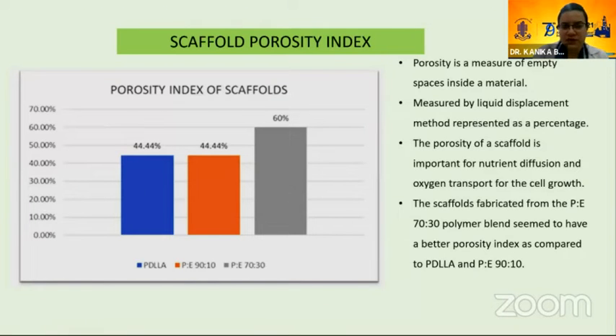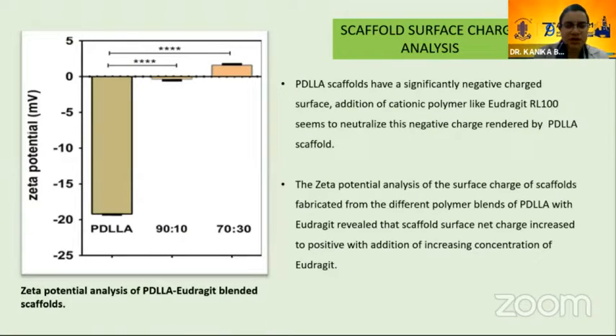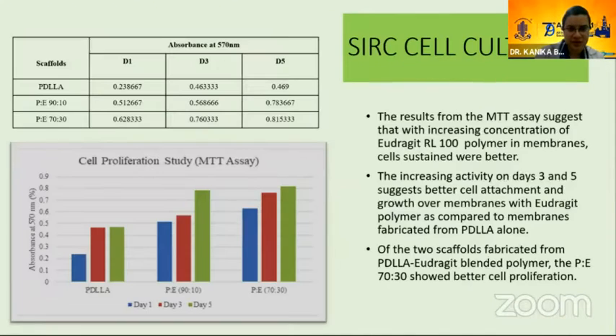Out of the scaffolds that we saw, the 70-30 combination ratio showed the best porosity, and porosity is necessary for diffusion of nutrients. Cell surface charge is negative, so it needs a positive surface to adhere. So addition of Eudragit to the PDLLA actually increased the surface charge and gave better cell adhesion.